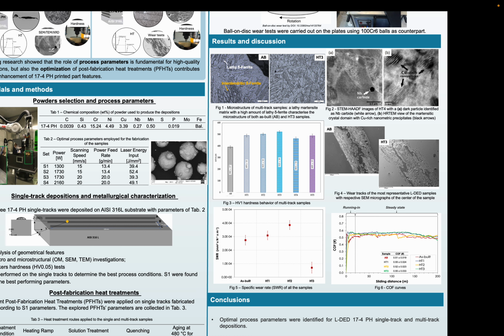A strong correlation of the microstructure and the post-treatment effect and the hardness was found, since, as observed in figure 3 of the hardness plot, the samples with higher values, such as HT3 and HT5, present the higher values of microhardness, which means that these samples did not suffer solubilization or solution treatment of the alloying elements, and no supersaturated solution was formed during the quenching. So, by TEM were identified the presence of nanometric strengthening precipitates such as copper-rich nanoparticles and niobium carbides, which were promoted in the case of the long aging time.